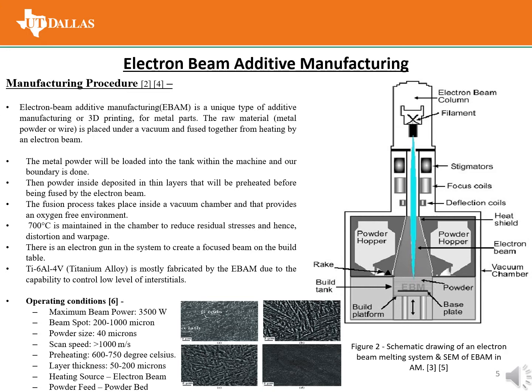Firstly, the metal powder will be loaded into the tank, then it will be preheated. Then, to reduce the residual stresses, 700 degrees Celsius is maintained in the chamber. Mainly titanium alloy is fabricated by EBM due to the capability to control the low level of interstitials. The operating conditions of EBM are also discussed here.